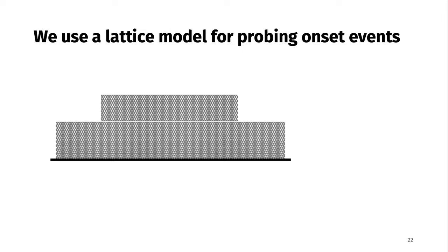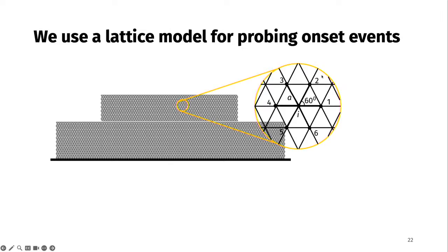I'll just give you the basic outline of what this lattice model does. So there are bulk bonds. The bottom and the top are both elastic. We make the bottom pseudo-rigid by increasing the stiffness significantly. The ratio of the stiffnesses is about 1:100.